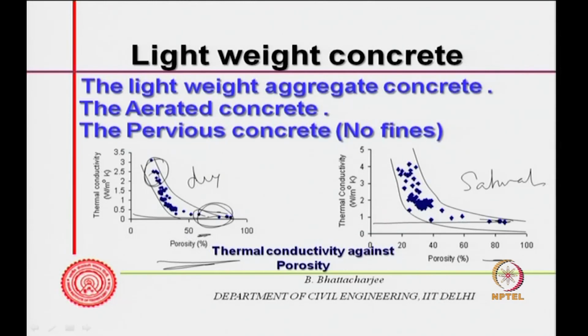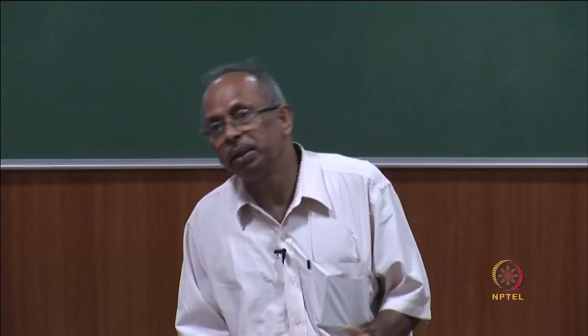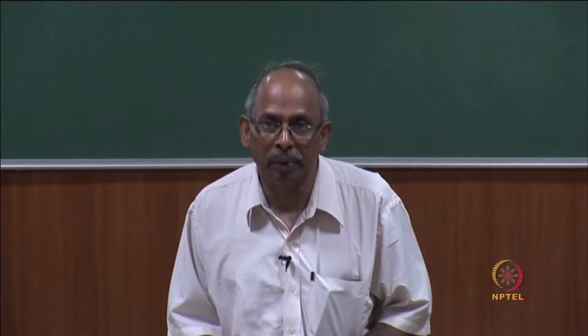While normal aggregates are here. This is for concrete actually. Normal aggregate would be somewhere there, 2.5, and at saturated condition 4, etc., with quartzite aggregate. Other aggregates might show you somewhere there. So, you see, you can generate actually lightweight concrete here, but even normal concrete, their thermal conductivities are of these varieties, orders are known to us. Saturated condition with moisture, they give you higher conductivities.